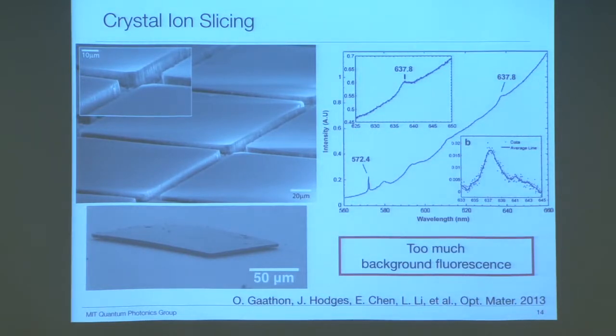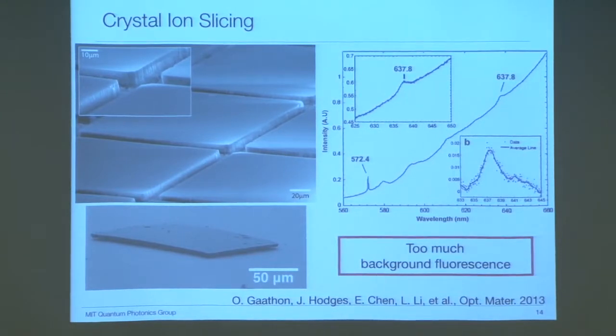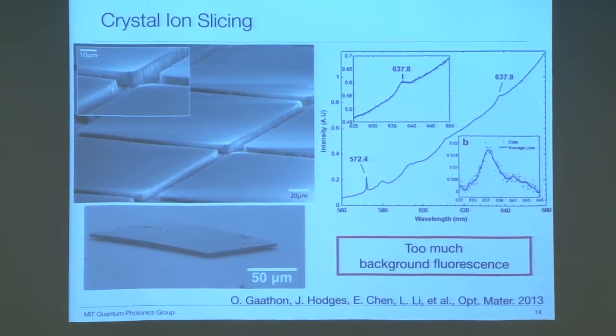This background means that this method does not produce diamond membranes that are of high enough quality for our applications. Sorry, what's the y-axis? Intensity of what? PL intensity, photoluminescence. And what's the temperature of the measurement? It's room temperature.